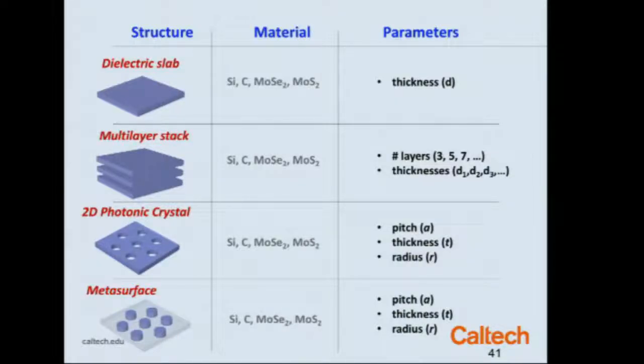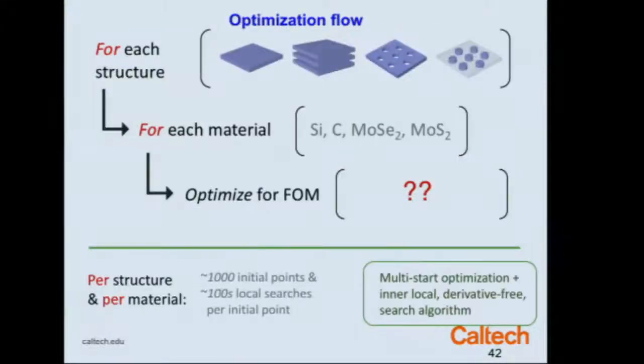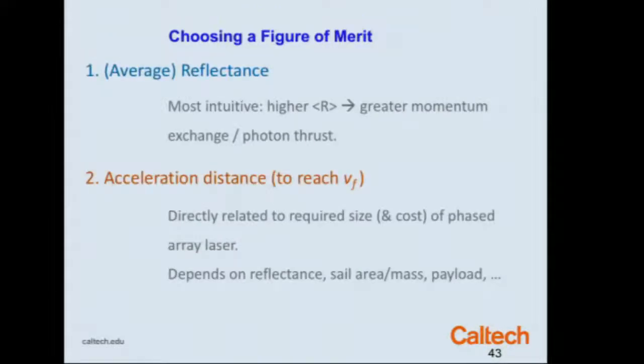And this is a structure that I talked to you about yesterday with arrays of antennas, in this case not metallic, because we need low absorption. These are dielectric antennas. And we've permuted all of these variables, the thickness, the number of layers, the period of these structures, their radius, and their height, through with a variety of different materials, silicon, diamond, and these two metal chalcogenides. So for each of them, we would like to find, to optimize them relative to some figure of merit. And the question is, what should that figure of merit be? So we started with thinking about what are the figure of merit, and we have many different points where we seeded the algorithm. And we decided there are a couple possible figures of merit.